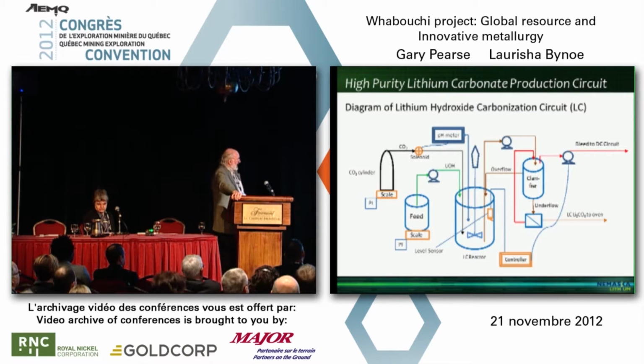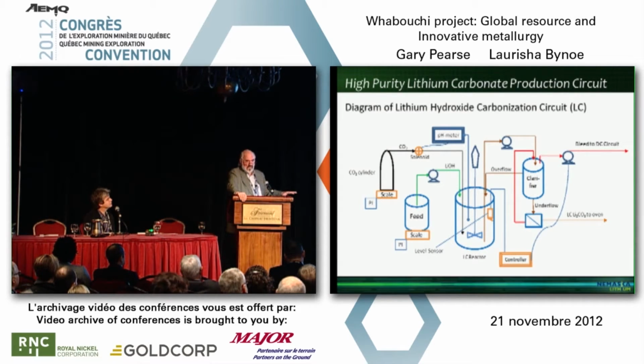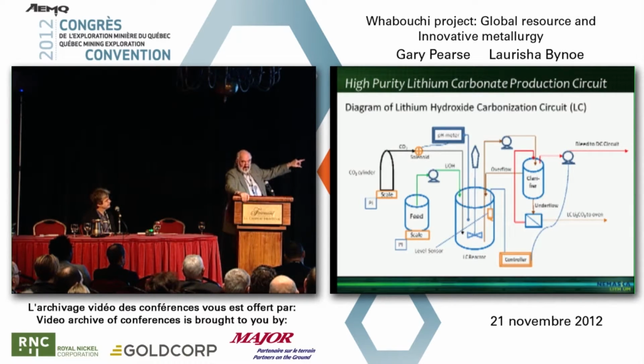Now, this is another innovative part of the processing, in that we can make what's called 4-9s lithium carbonate directly with no middling product and essentially very little waste. It's a 93.7% recovery of lithium carbonate, and using lithium hydroxide, very pure lithium hydroxide product. We can put some through there and so on. The beauty of the situation with this